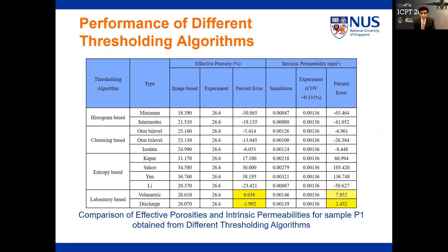We found that the error percentage for effective porosity can vary from minus 30% to a maximum of plus 38%. For permeability, it can vary even more, from minus 65% to up to 136%. Even the laboratory-based volumetric method can produce an error of 8% for permeability. Our own discharge-based algorithm produces the least error, with respect to porosity and permeability, of minus 2% and plus 2.5%, respectively.